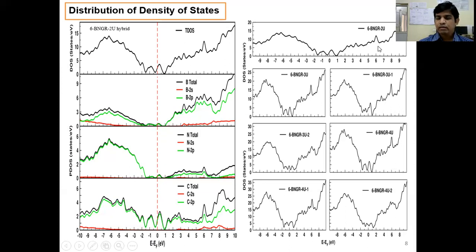So all the states belong to the nature of a conductor. We can see when a single atomic layer is transformed into a 2-layer, 3-layer with vacancies, and 4-layer, what kind of thing is observed. We can see no forbidden energy gap with 2 layers. By further increasing the length and width, we can see further enhancement in the density of states of the ground state electrons.